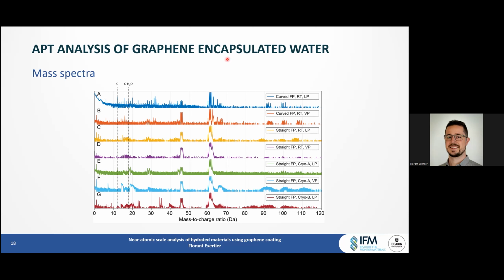Another key aspect to note is that there are no molecular ions corresponding to water that are larger than 45 Dalton, as opposed to other atom probe studies on larger volumes of water, where the heaviest detected ions went beyond 100 Daltons. In this work, the peaks heavier than 45 come from the tungsten substrate and also occasionally the copper from the graphene etching.